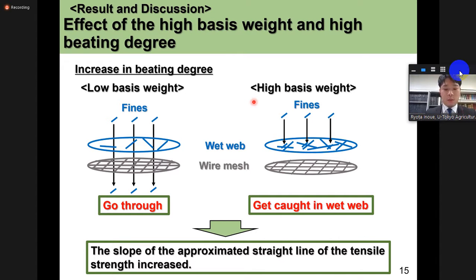In this slide, I'd like to discuss why the tensile strength is efficiently increased by the combination of high base weight and high beating degree. First, I consider the case where the beating degree is increased with low base weight. Fibers larger than the wire mesh make up the wet web, so fines go through the wire mesh and fall off. On the other hand, I consider the case where the beating degree is increased with high base weight. Because we use a lot of pulp to make hand sheets, fines get caught in the wet web formed earlier. So these fines may improve the paper strength. This can explain why the slope of the approximated straight line of the tensile strength increased.